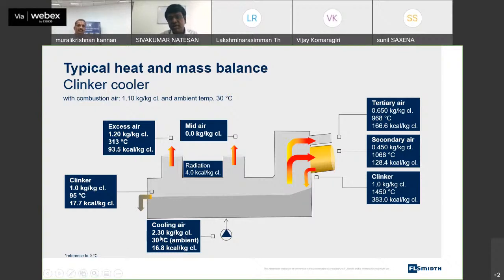You can see that we are using generally close to 2.3 kg of air, when the previous generation coolers used to take 2.6. Even the old generation will take 3 kg for the same clinker temperature. So this is evident that for attaining the same clinker temperature, this cooler uses lower airflow, and that results in high quality heat in the excess air, because you can see that the excess air temperature is 313. That is because the cooler efficiency till the last row is high, and the higher recuperation makes the heat transfer better. So you have high quality heat in the vent.